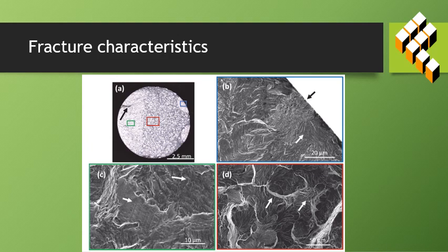On the fracture surface of the specimens used for the rotating bending test, the distribution of the number of cracks along the free surface varies per test specimen. Despite this, in all the specimens that failed, a single fatigue crack seems recognized to propagate and cover a relatively large area.